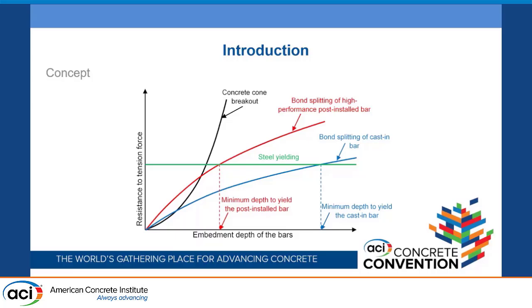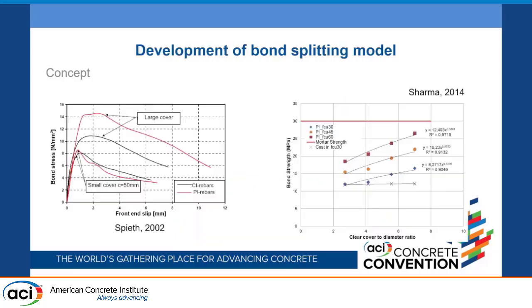So he said, why don't we bring all of them together on one chart, which means we consider all possible failure modes, including concrete cone breakout and steel yielding, but we need something new for bond splitting of high-performance post-installed bars, because they are going to perform better than the cast-in bars. This concept was also investigated long back. One PhD student of Professor Eligehausen did this in 2002, and he showed that at small cover, cast-in rebar and post-installed rebar behave similarly, but at large cover, post-installed rebar gives higher strength, depending of course on the type of mortar used.